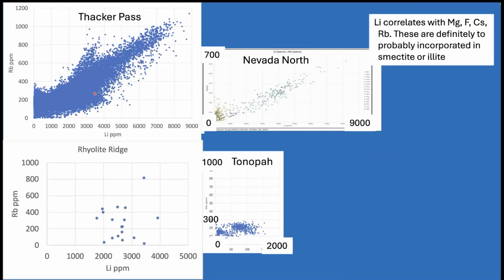Okay, several other elements. Here's rubidium, which is geochemically like lithium and definitely follows it. It has the same sort of trends. For Thacker Pass, this would be the illite trend going to the higher lithium concentrations, higher rubidium concentrations. This would be the smectite trend, lower lithium. And there's also this oddball thing of higher rubidium, but not real high lithium. And we see that to some extent at Nevada North.